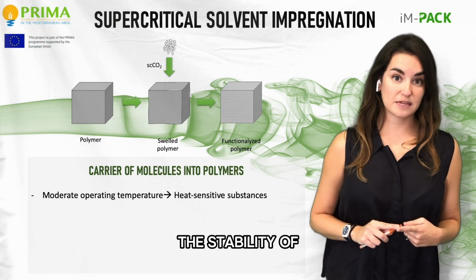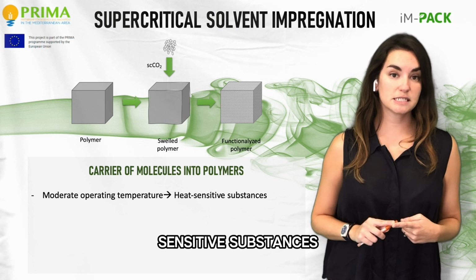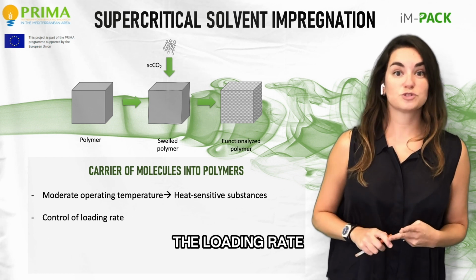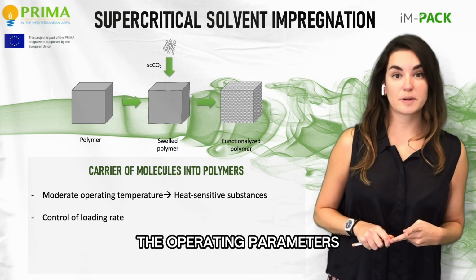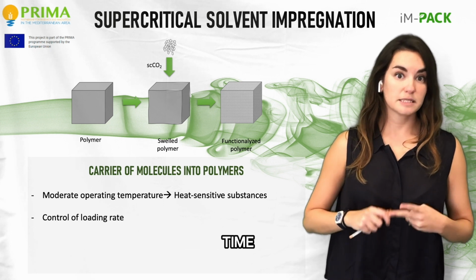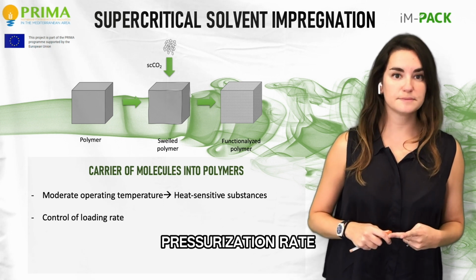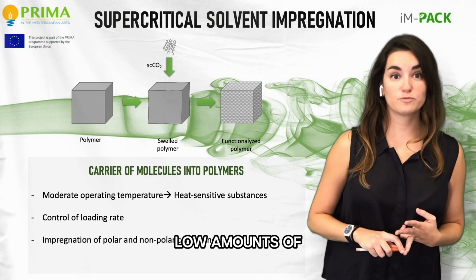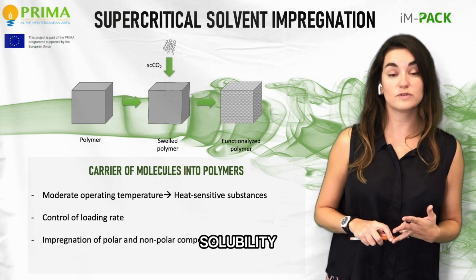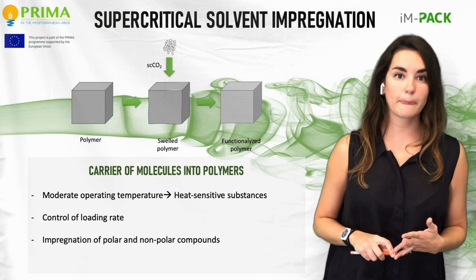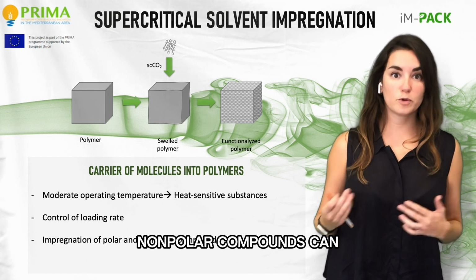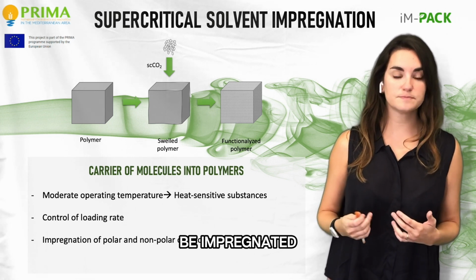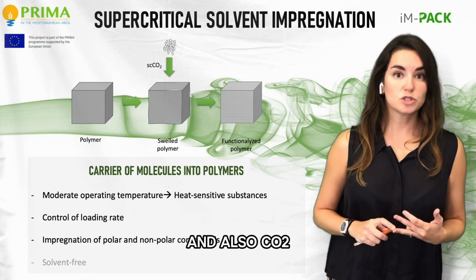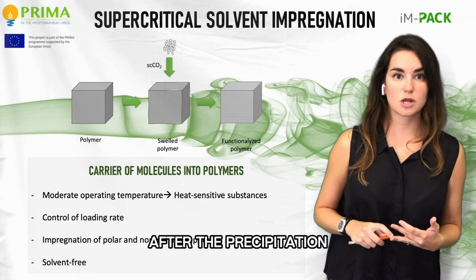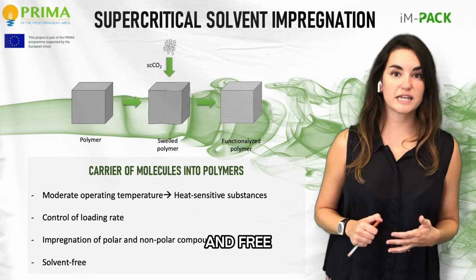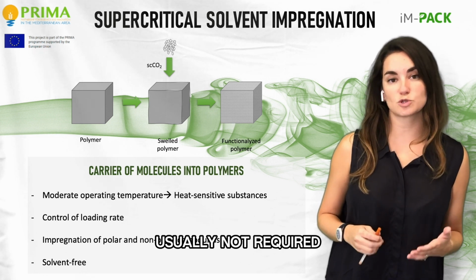that do not compromise the stability of heat-sensitive substances. The loading rate can be controlled by modifying the operating parameters, such as pressure, time, temperature, or the pressurization rate. Low amounts of polar solvents can be added to enhance the solubility of compounds in the CO2. Therefore, both polar and non-polar compounds can be impregnated. And also, CO2 turns into gas after depressurization, so the polymers obtained are solvent-free and the final evaporation step is usually not required.